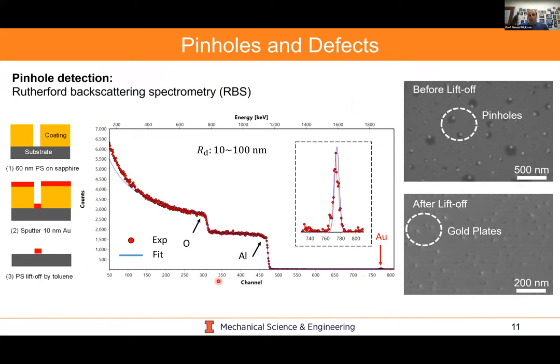So to give further proof of the presence of these pinholes, SEM for us wasn't enough. We actually took a look at another characterization technique called Rutherford backscattering spectrometry. This is a very interesting technique where what we could do is take a substrate, deposit our coating. We then sputter a 10 nanometer deposition of gold, which is directional, on the coating. We then do a liftoff process to remove the coating. And then we could do Rutherford backscattering spectrometry, RBS, to see whether we could sense heavy metals and get their density.